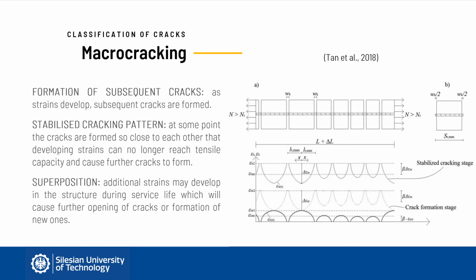Nevertheless, additional strains may develop in such a cracked element during its service life. Such additional loading may lead to formation of further cracks or opening of the existing ones. The latter case is especially dangerous because it may lead to exceeding the allowable limit value of the crack width.